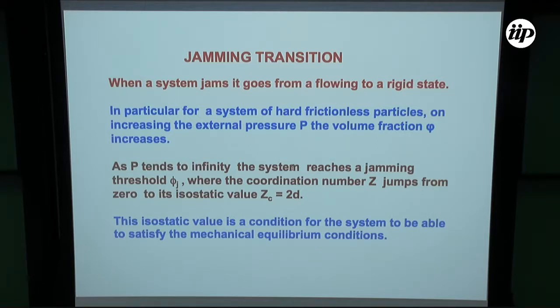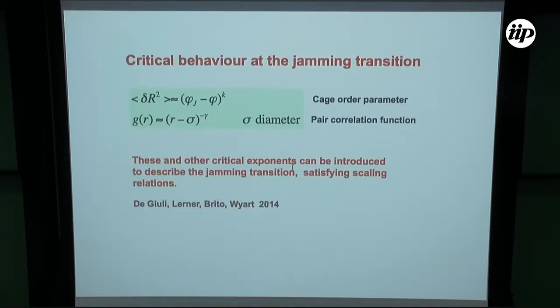So from this phenomenology, you understand that the transition is a kind of first-order transition, because zeta jumps from 0 to a finite value. However, there is also a critical behavior, more typical of a second-order, continuous transition, which can be described by different exponents. One is this delta R squared, the so-called cage order parameter, where delta R is essentially the linear dimension of the cage in which the particle is jammed. And as you reach the critical threshold, this quantity goes to zero according to this power law.